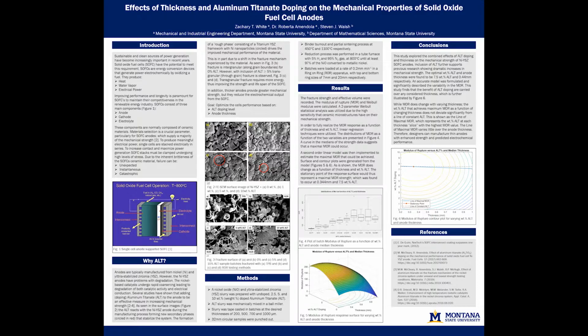Anodes are commonly manufactured from nickel oxide and yttrium stabilized zirconia, or YSZ. These materials have longevity issues due to rapid coarsening of the grain microstructure from their use at high temperatures. This directly reduces power output, severely hampering the operational lifetime of the SOFC. Many recent studies have found that by addition of aluminum titanate, the anode is not only stabilized but displays improved mechanical strength. Doping the nickel oxide YSZ system with aluminum titanate leads to the formation of secondary phases that restrict the nickel from coarsening and provide particle anchoring.